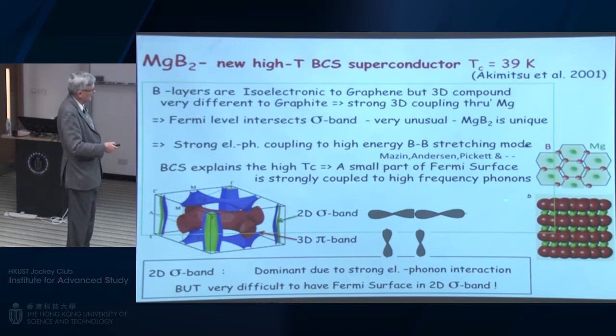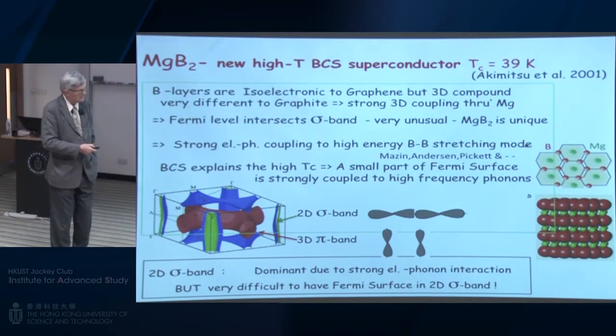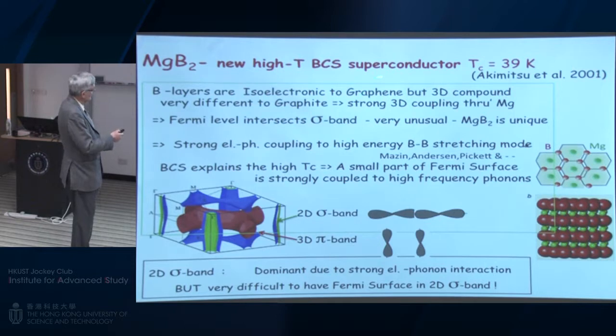If we look at the structure of it, then what we see is boron layers interspersed with magnesium layers here. And the magnesium essentially donates 2 electrons to the boron. So these boron layers are actually isoelectronic with graphene, which is a material which has been very much in the news with the Nobel Prize and all that in the last number of years. But the electronic structure is quite different to graphene, or graphite, the three-dimensional version of graphene, because here the coupling between these boron layers through the magnesium is much stronger.